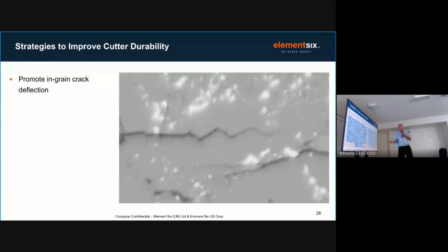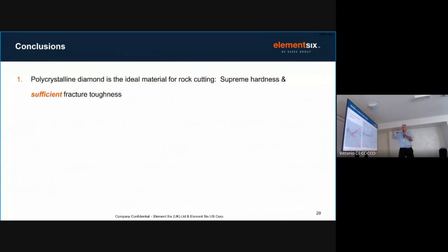This I thought was a nice thing for the crack paths community. We seem to be getting in-grain crack deflection. So this would be one diamond grain. Excuse the poor quality of the micrograph, but that's about 70-degree crack deflection as we go, which is the angle between the 111 planes. It would be better if that were exactly 70, but never mind.